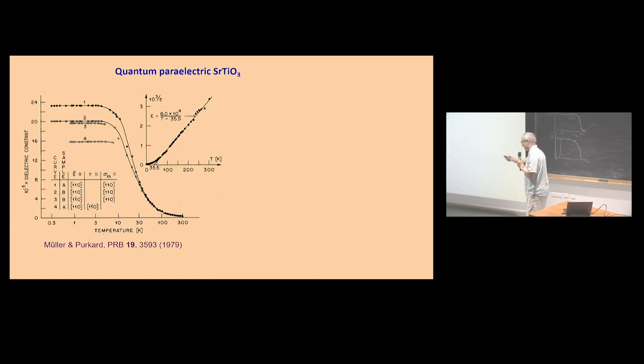Strontium titanate, I mentioned already before. What does it mean? Here, it's not ferroelectric, but it is a so-called incipient ferroelectric or quantum paraelectric system. Here is the result of the temperature dependence of permittivity versus the logarithm of temperature. Note that it is a logarithm. And there is an increase of permittivity which follows the Curie-Weiss law. And if you plot inverse permittivity, you get 0 at 35 Kelvin. So it looks like a ferroelectric phase transition should appear at this temperature. But it's not appearing due to quantum fluctuations.